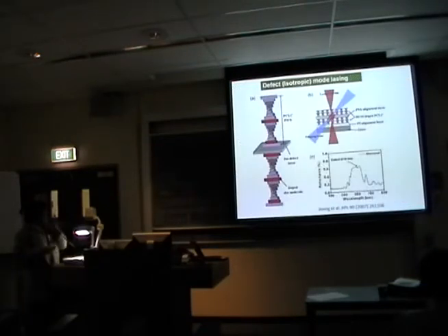Then we also made an isotropic defect layer. We insert the isotropic defect layers. We use a polymeric liquid crystal, as I mentioned, and we insert a polymer layer. Actually, we use PVA, and we made this kind of structure: cholesteric, isotropic polymer film, and cholesteric.